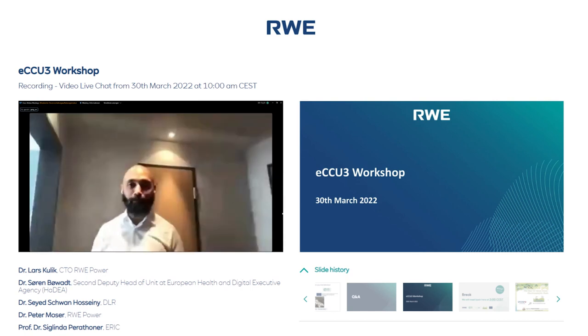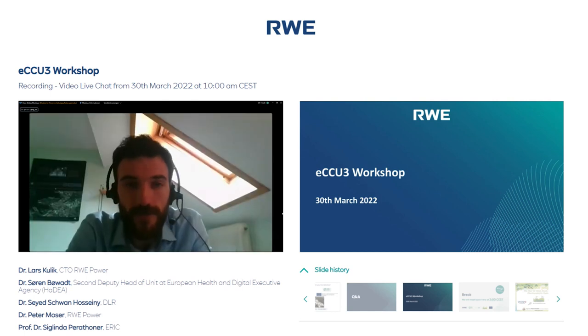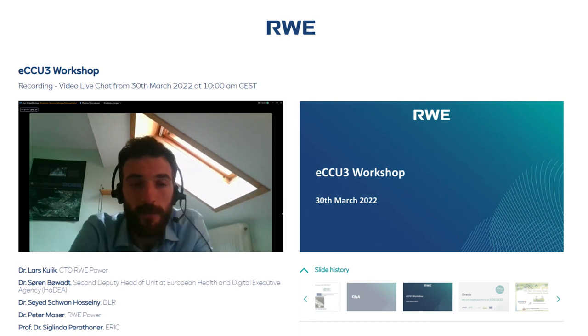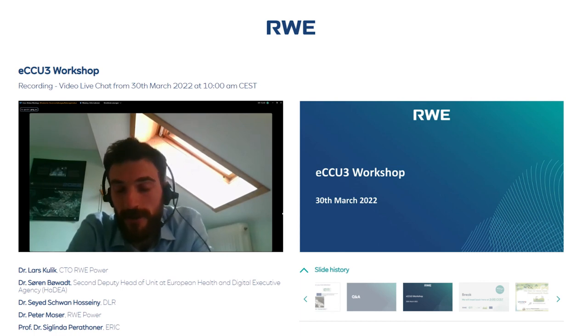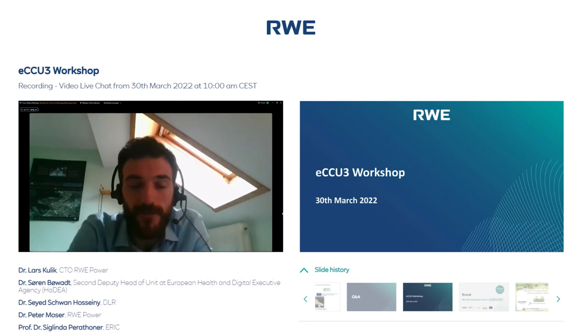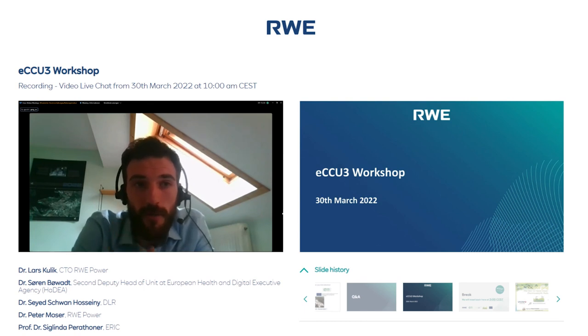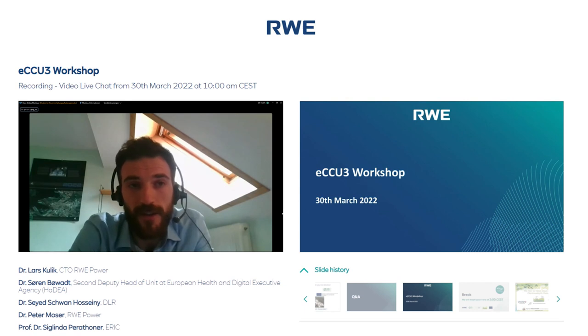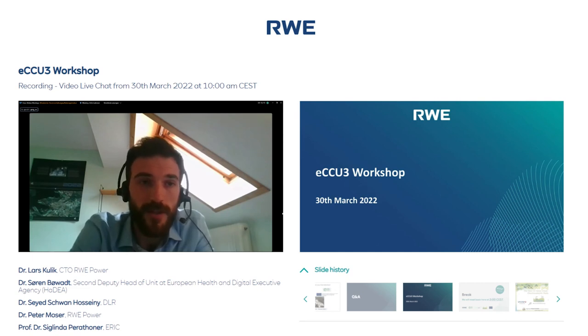Simon, do you know why the catalysts change their morphology? So, as Antonino mentioned, we have an oxide material, copper oxide, that is present here. And during this reductive operation, we have a reduction of this oxide to metallic copper, usually. And this can be avoided, obviously, by adding some elements, but it's still happening in our case. And during this reduction process, some copper atoms will dissolve into the solution and then redeposit again, probably into this metallic dendrite structure that I have shown there. So it's basically a dissolution-redeposition process that is occurring here.